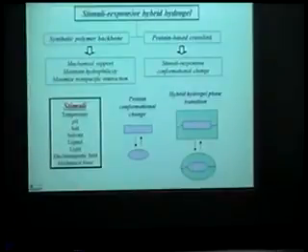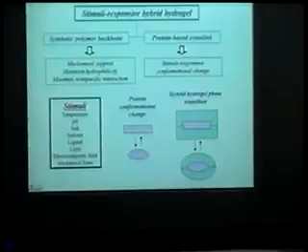One is based on synthetic materials. We intend to use this as a mechanical support, to absorb water to keep everything swelling in water, and to minimize non-specific interactions involved in the second component, which is based on proteins. The proteins here are actually the vital component, where we're trying to take advantage of the stimuli-responsive behaviors of protein conformational change to drive a macroscopic property change of these hydrogels.